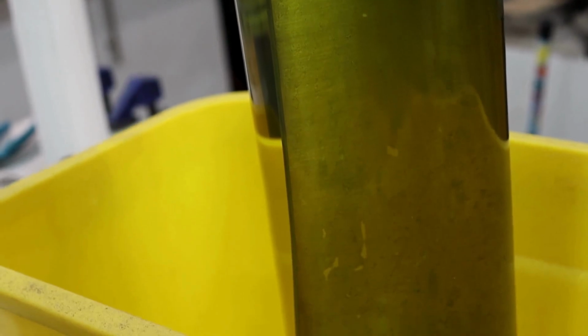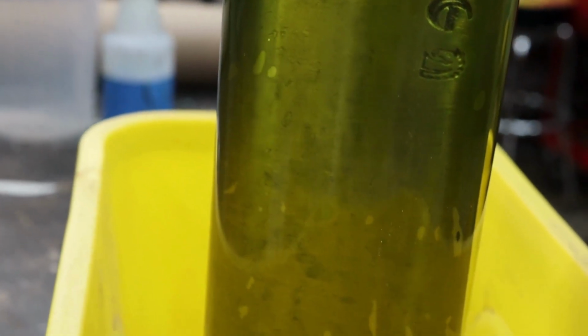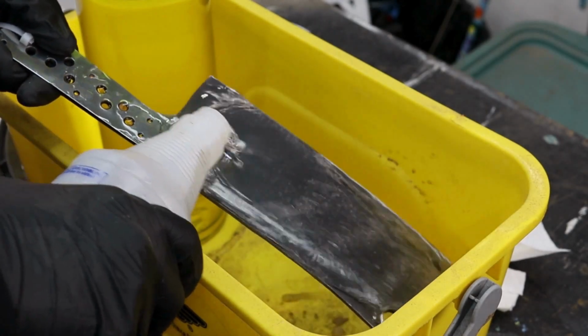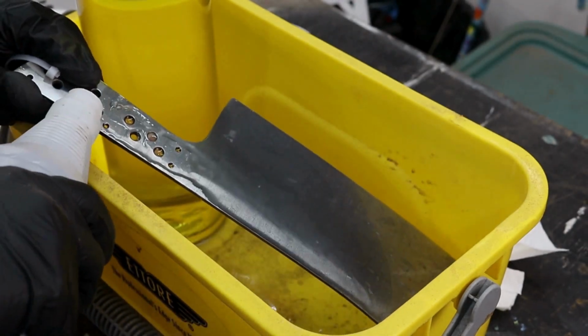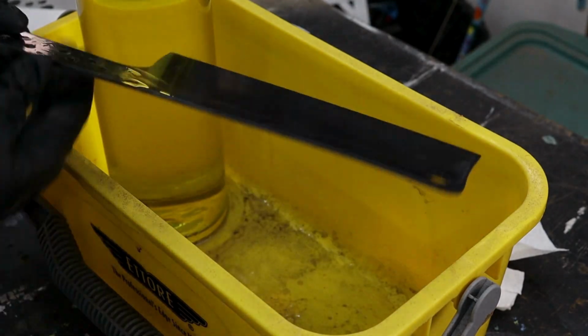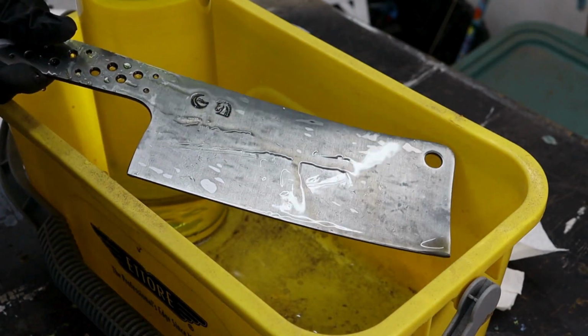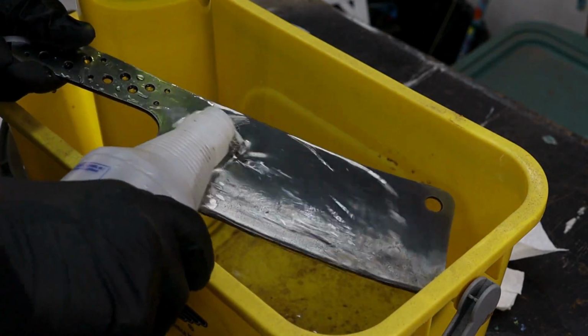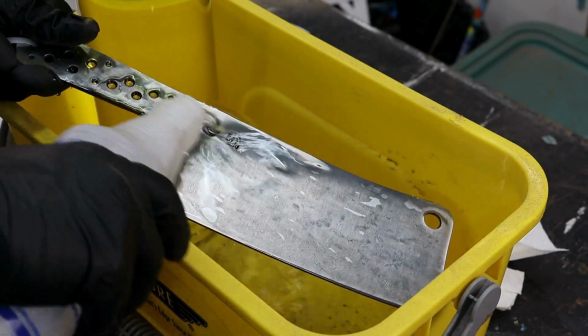I let the blade soak in Gator Piss for around 10 minutes since this is just a test etch, and then I neutralized the acid with a mixture of baking soda and water. That's kind of a bummer. You can see some spots where I just barely ground through the Damascus, and you can see the inner layers of 15N20 peeking through. But the core layer of 1084 looks really well centered across the entire blade.